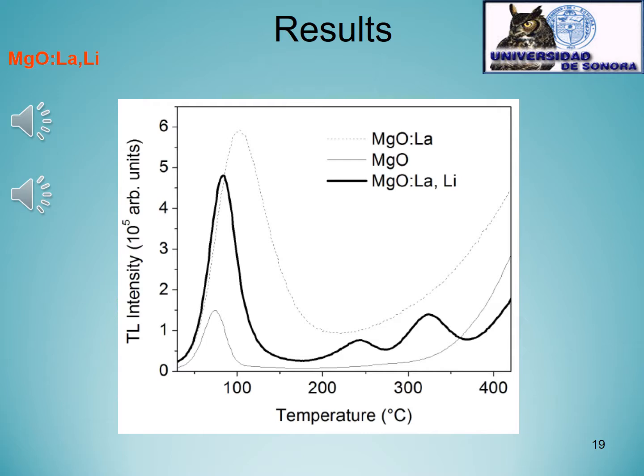a significant difference between the other two TL glow curves, because in this case there is the appearance of two different components at very stable temperatures, and we have this low temperature peak, which can be useful for other applications such as persistent luminescence application or afterglow.